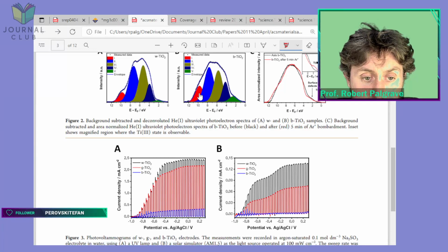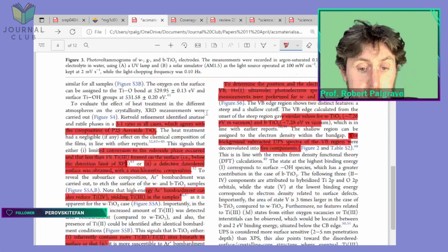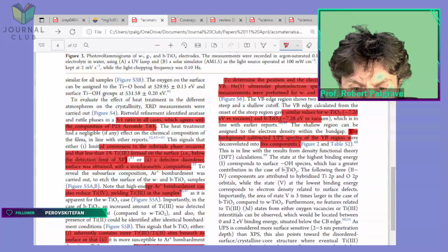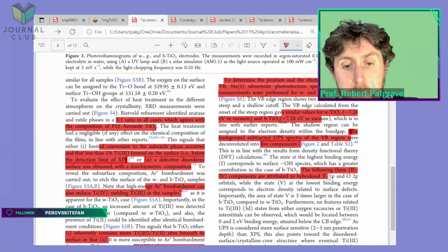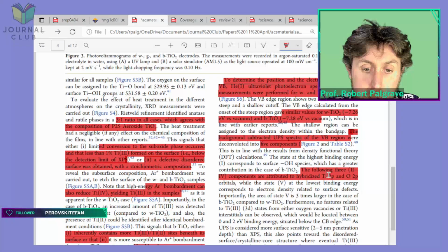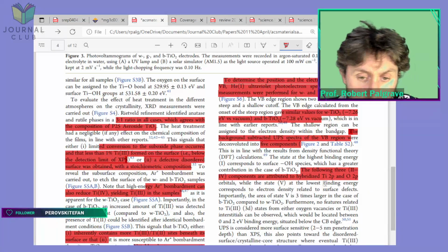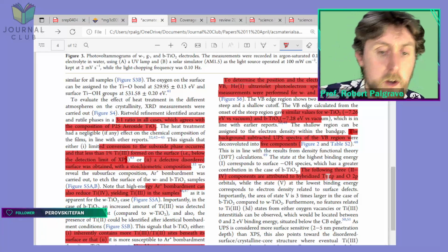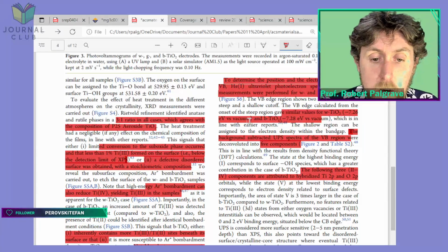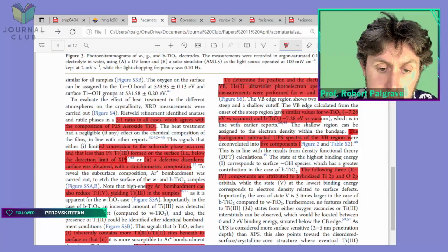So that's this thing here, apparently, surface OH species. Fine. The following 3, 2 to 4, are attributed to hybridized titanium 2p and oxygen 2p. Okay, I think this is probably a typo. I think they probably mean titanium 3p. So titanium 2p is a core orbital. In fact, they even showed spectra from titanium 2p. So I think they mean titanium 3p.